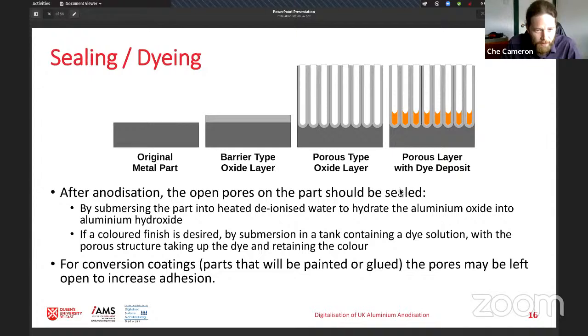And very, very commonly, it's put into a dye bath, and the dye molecules will go inside the pores and they will retain that color, and that's how you get a colored anodized part. And conversion coatings, which I'll talk about a little bit later, use the pores a slightly different way, but they still make use of the fact that the pores will uptake whatever they're exposed to.